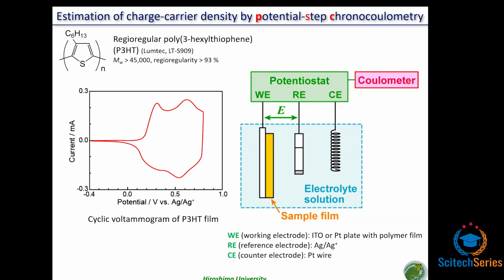Here I show the cyclic voltammogram of the P3HT film obtained by this system. At minus 0.4 volt, no current is flowing and P3HT is in neutral state. When the potential was shifted to the positive side from minus 0.4 volt, anodic current was observed from around 0.2 volt. It suggests that the P3HT is oxidized in this potential region.